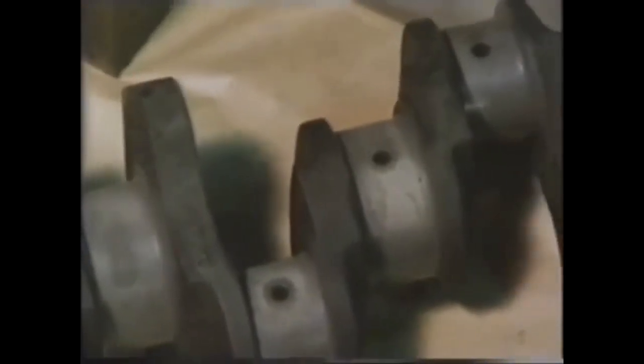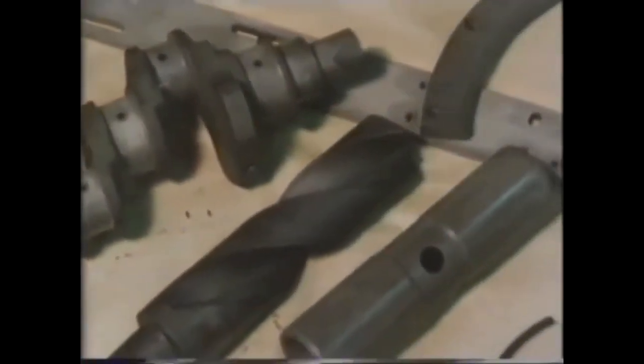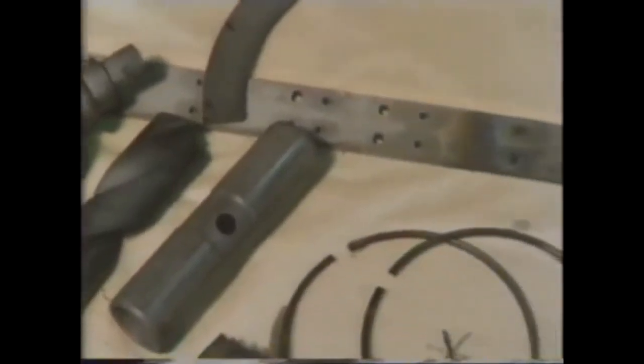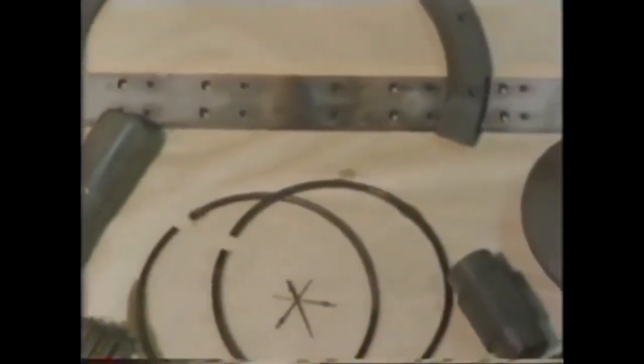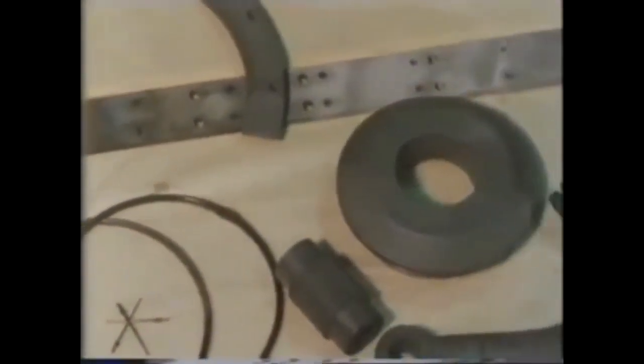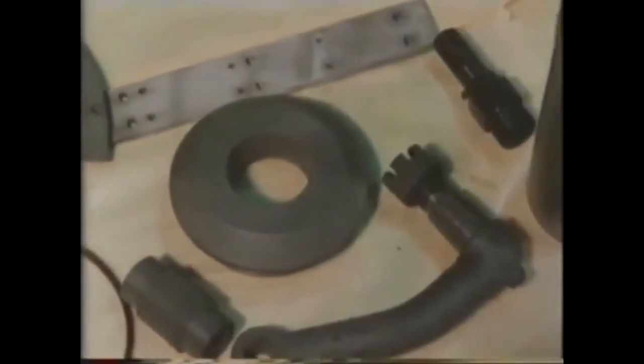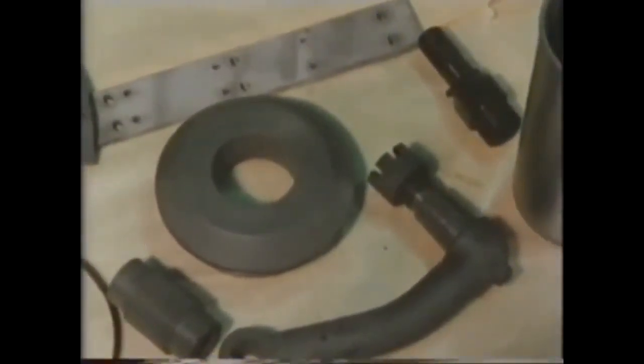Nitriding resembles carburizing in that the steel is heated for a time in the hardening medium. For carburizing, it's carbon. In nitriding, it's nitrogen. But for nitriding, it's important to have special alloy steels which contain small amounts of metals like chromium and vanadium. The nitrides formed from these metals harden the surface of the steel.